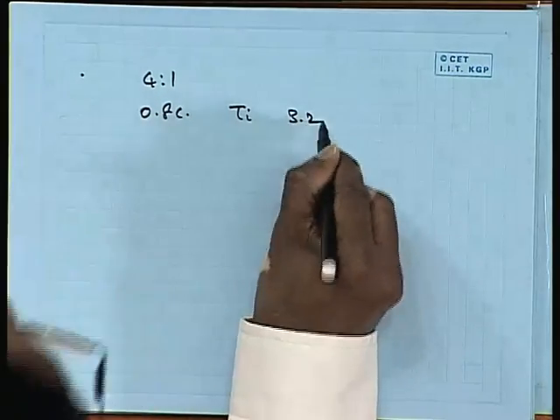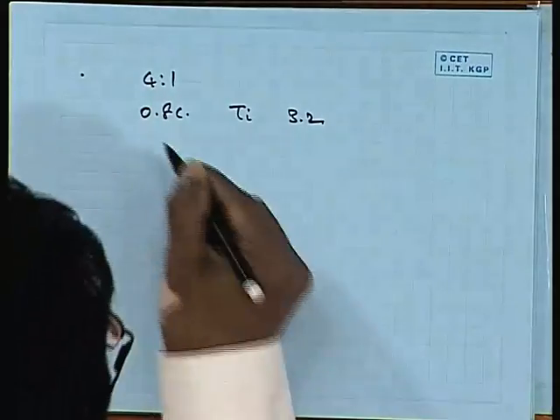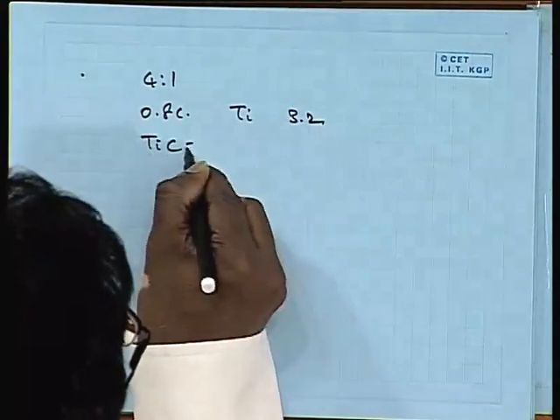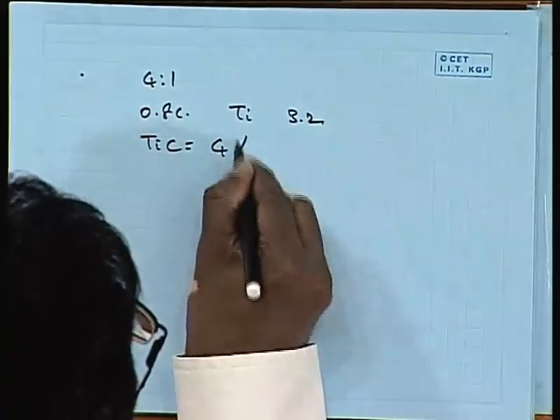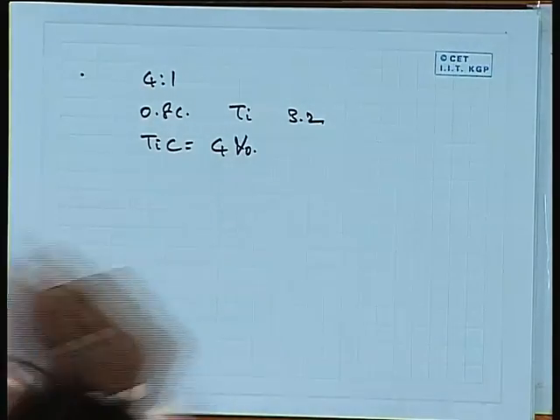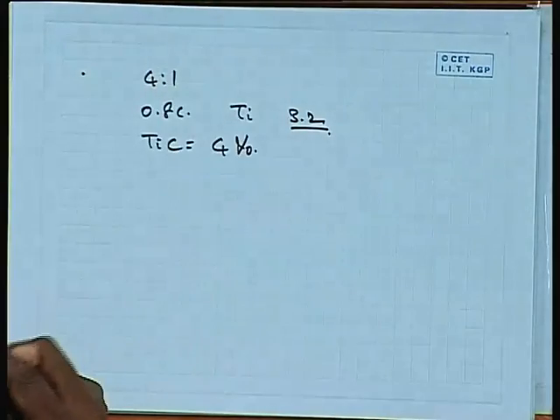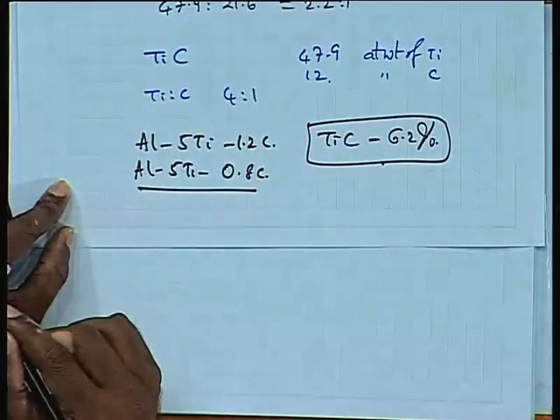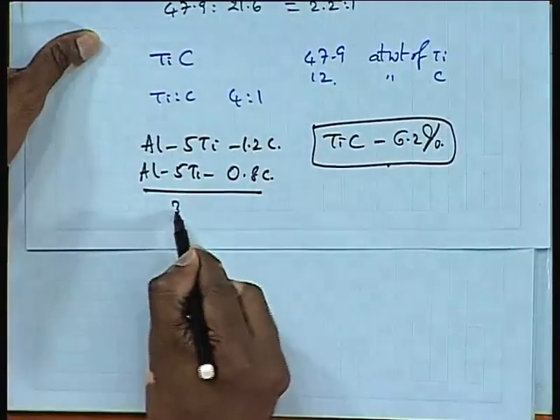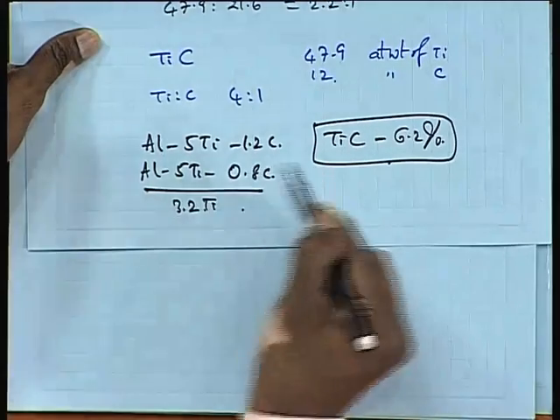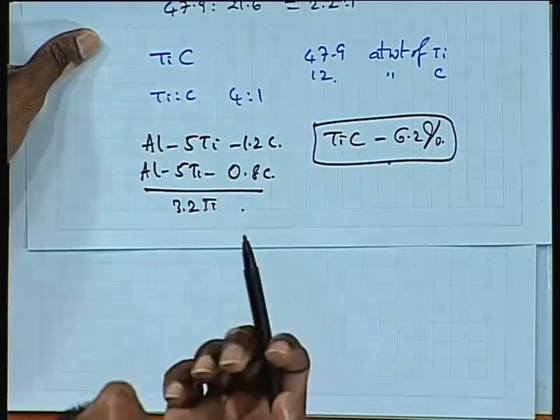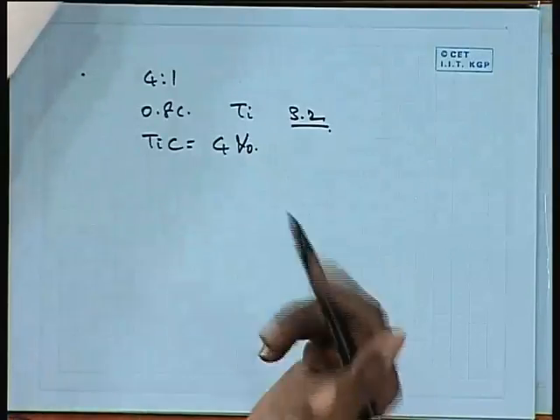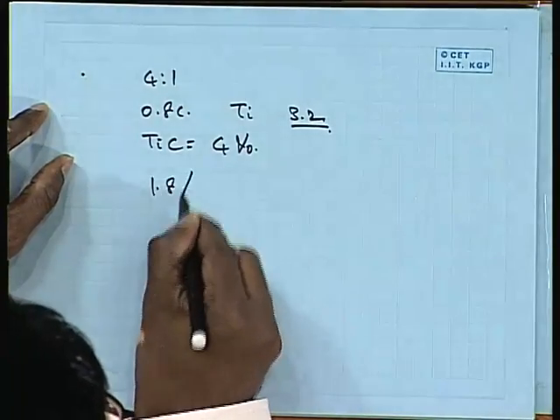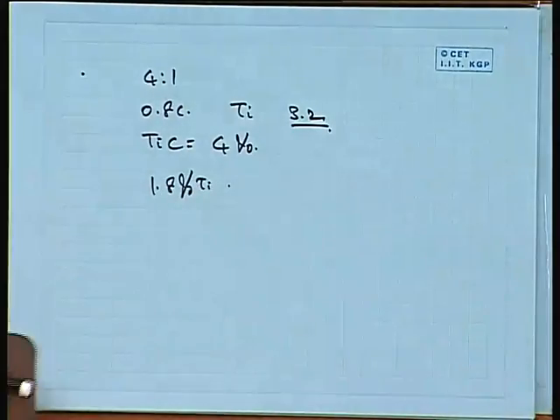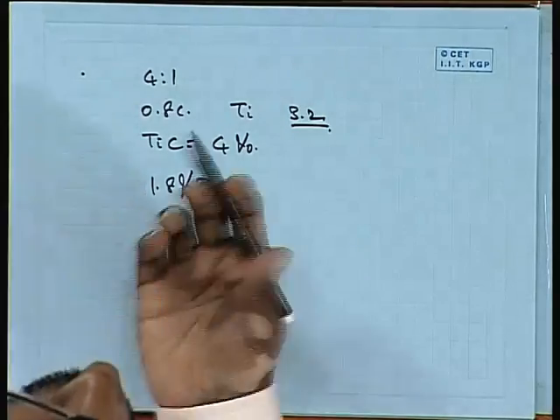3.2, fine. So, what will be the volume weight fraction of TiC? 4%, 4% of TiC will form. Now, if I take 5% of titanium alloy, this is the alloy that I am talking about. In 5% titanium, 3.2 of titanium has already gone and reacted with carbon. So, what is left out? 1.8%. So, that 1.8% titanium will react with the aluminum to give you TiAl3.